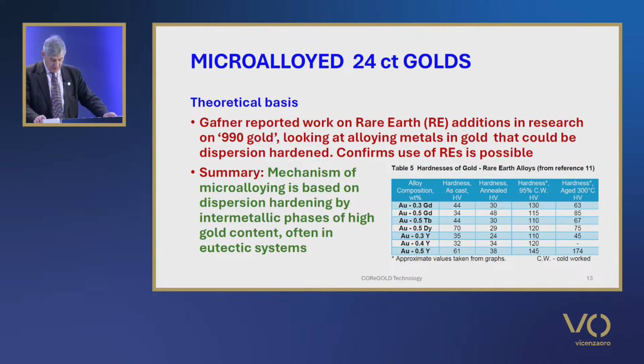From this, a table of probable hardening effectiveness was constructed, and I haven't put it on the slide, but it is in the written paper, which you can get when it's loaded up on the website. The fraction of hardening phase was taken as an indication of the hardening effectiveness. The reason for developing the 990 gold titanium alloy is obvious from this table, as it has the highest fraction. The promise of the rare earths and zirconium was also noted.